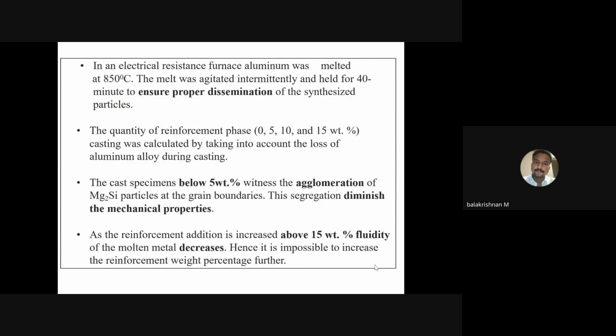Then again, for the intermetallic reaction, how much temperature we have to maintain and for what time we have to maintain. Actually in this process 850 degrees centigrade is maintained for 40 minutes to ensure proper dissemination of material. Then quantity of reinforcement as per the calculation I have shown in the Excel sheet, that is 5, 10 and 15%. Then casting specimen below 5%.